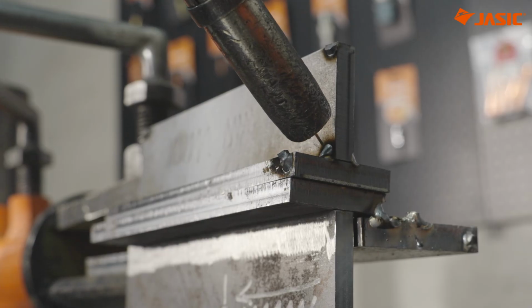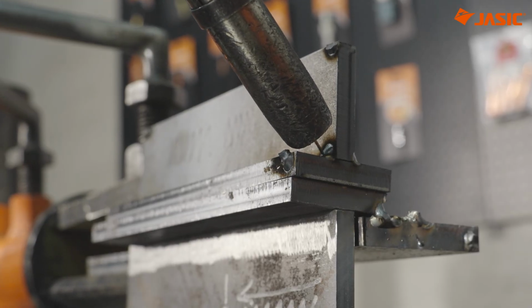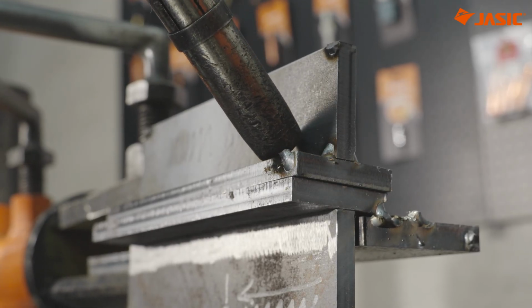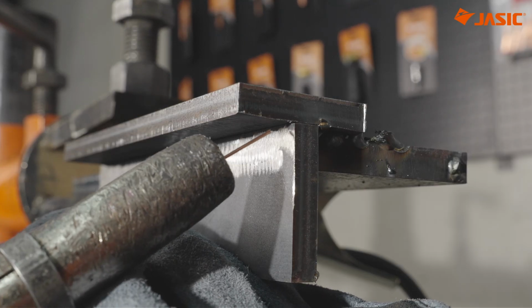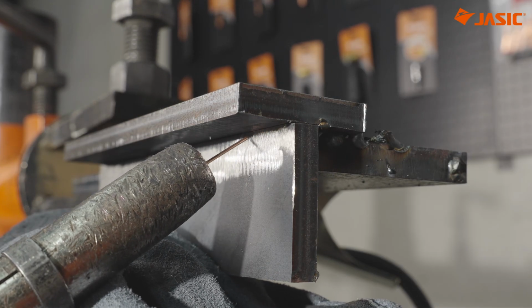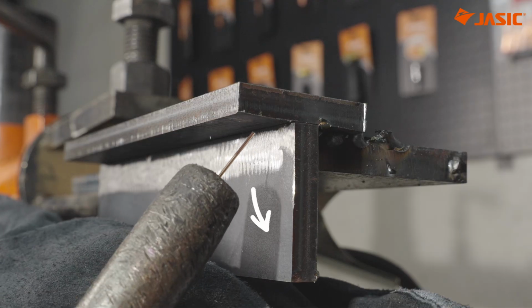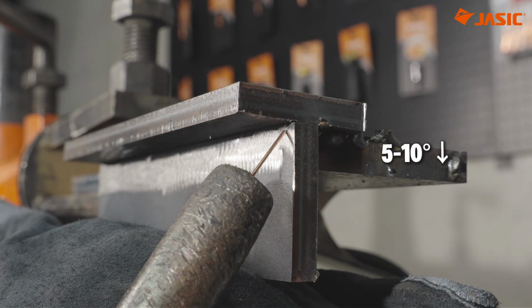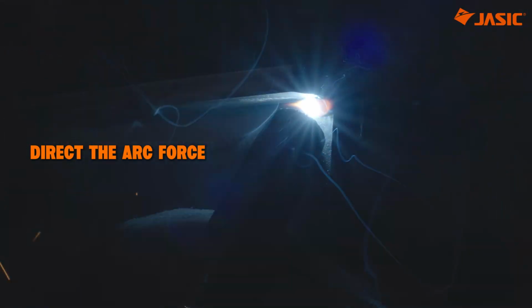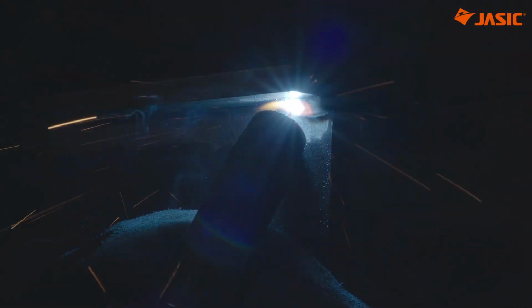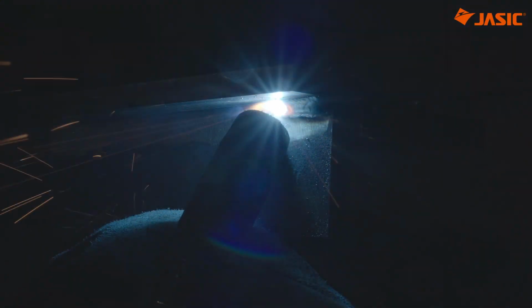When doing a standard fillet weld, the welding gun is usually positioned at roughly 45 degrees between the 2 plates. But overhead welding is different. Starting from that 45-degree position, angle the gun downward by another 5 to 10 degrees. This helps direct the arc force against the upper side of the joint, keeping the molten pool from sagging or forming a bead that hangs down.